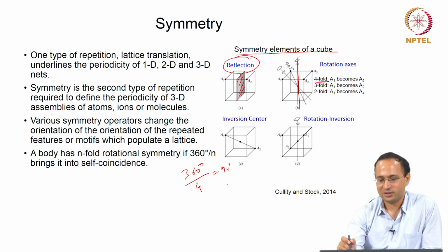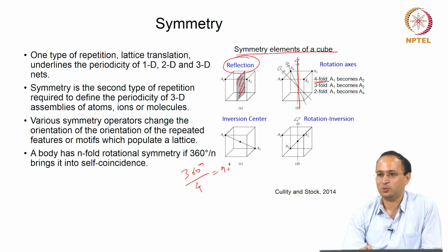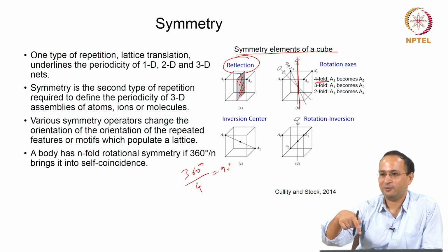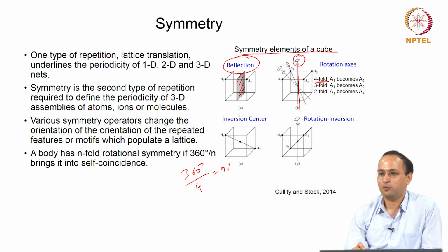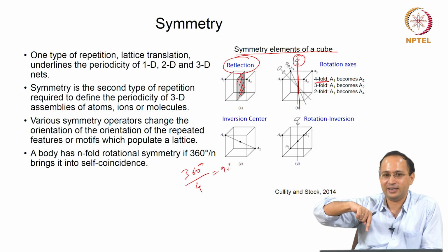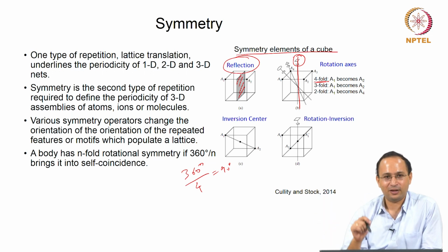After 90 degree rotation your A1 point becomes A2, similarly A2 becomes A3, that is this symmetry, 4-fold. 4 is coming from 360 over 4, 90 degrees. If you rotate 90 degrees, 90 degrees, 90 degrees, you will not be able to distinguish, clear.